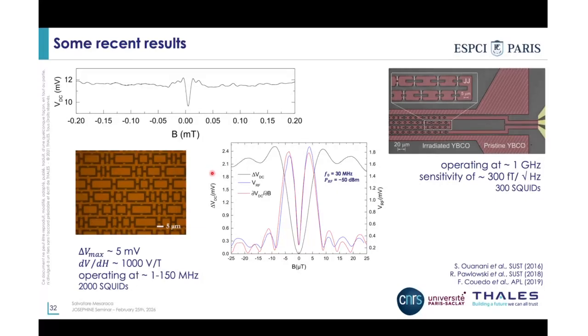As I said, we deal with these difficulties on a daily basis, and we try to improve them throughout the time. Here you can see a few results that we obtained over the past in our lab. The publications are here down on the right. You can see that we obtain devices with SQIF behavior with different configurations, and that we tested in the range from 1 to 150 megahertz, and sometimes in other publications up to 1 gigahertz, with different configurations and with different sensitivity as well, and with different numbers of SQUIDs.